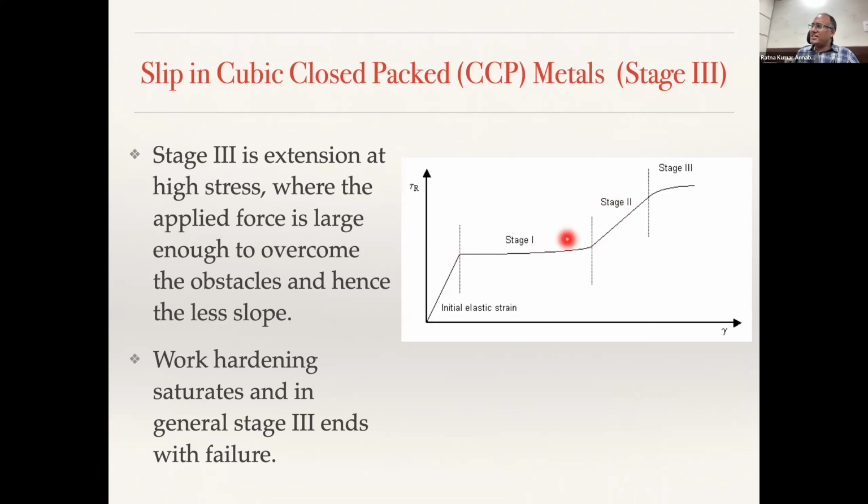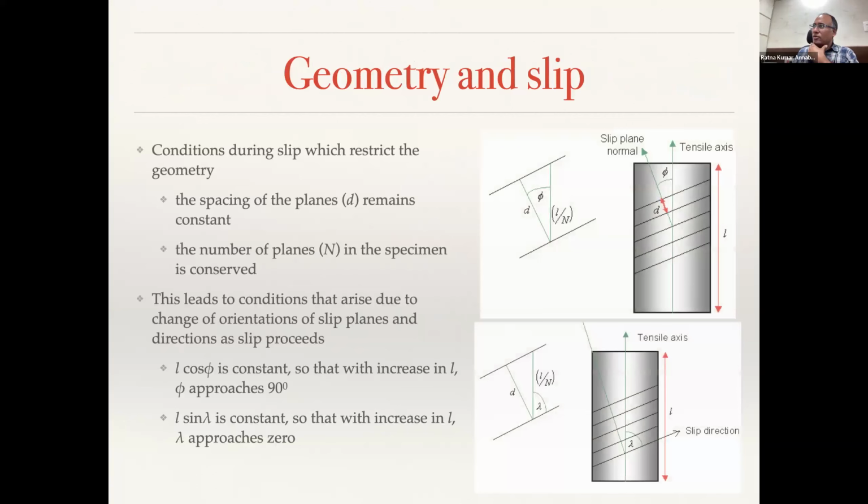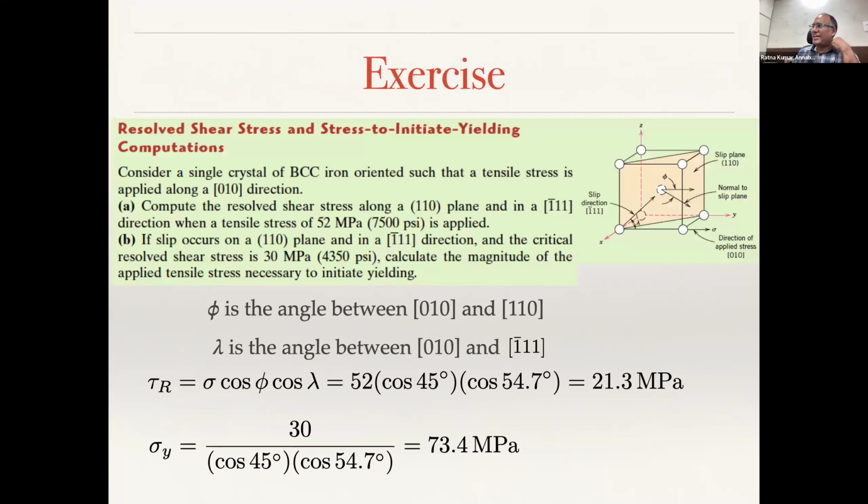The reason for that is there are multiple slip systems active at the same time, and there are so many grains and so many dislocations interacting with the grains, and hence you will not see this easy glide in polycrystalline materials. As soon as the plastic deformation initiates, they immediately start interacting with the neighboring grains, and as a result, you start seeing hardening from the beginning itself. Is that clear? Why in polycrystalline materials the easy glide is not there?